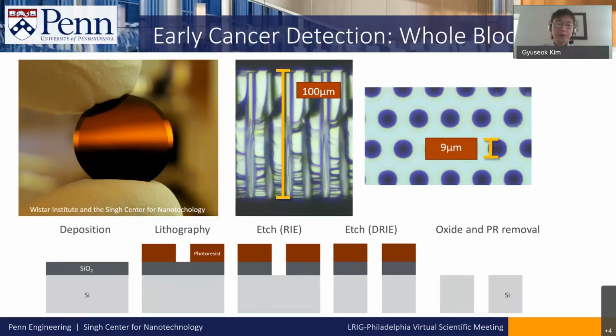The key challenge of this process was the high aspect ratio, and the process flow was this: we started with silicon, and we deposited silicon dioxide. We did lithography, and we etched the silicon dioxide with an RIE tool. And then we etched the silicon all the way through with the deep RIE tool. Then if we remove the oxide layer and the photoresist, we have the freestanding silicon device.